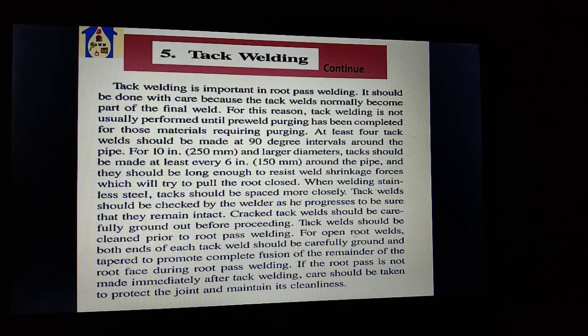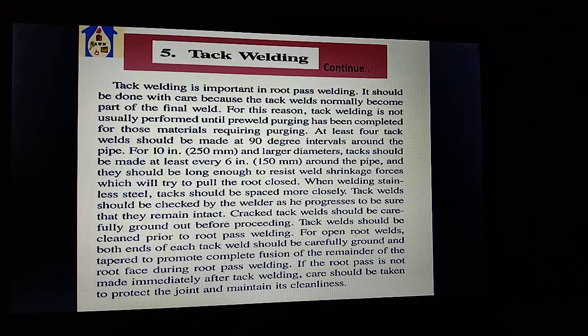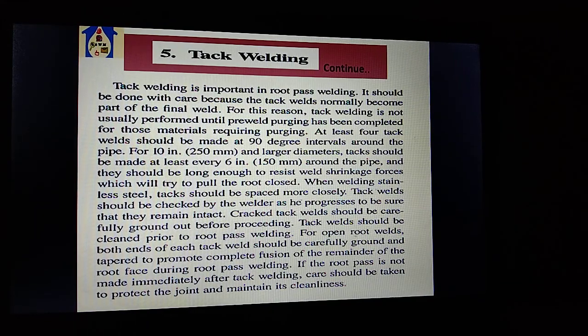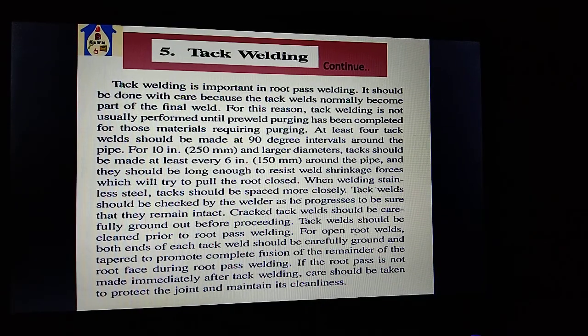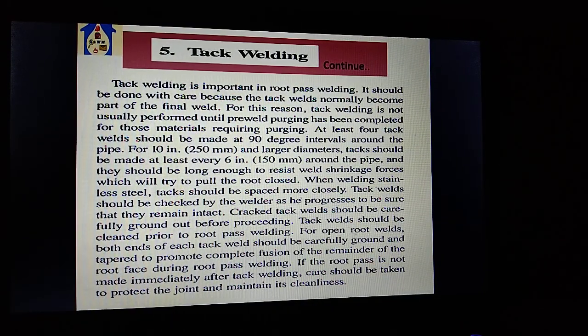When welding stainless steel, tacks should be spaced more closely. Tack welds should be checked by the welder as welding progresses to be sure that they remain intact. Tack welds should be cut out or fully ground out before proceeding. Tack welds should be cleaned prior to root pass welding.